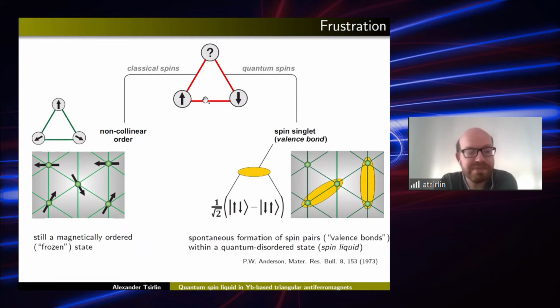So if I treat frustration alone, if I, let's say, put classical spins on this triangle, then they're still going to show some kind of magnetic order, this 120 degrees order. It's like not perfect for any of them, but it's good enough so that they can gain some additional energy from this kind of non-collinear ordering, right? So that's a sort of compromise configuration between being up-down. So all of them lose some energy by being non-collinear, but still gain some energy by aligning at 120 degrees relative to each other.